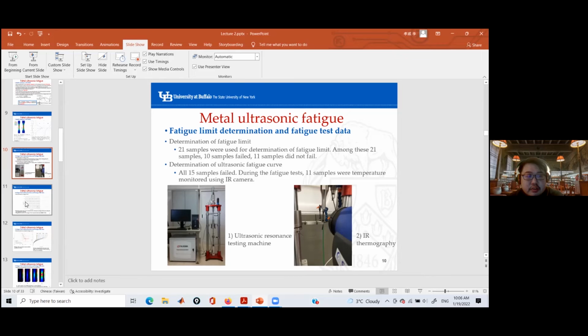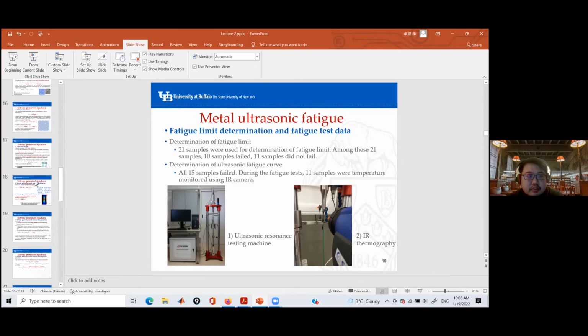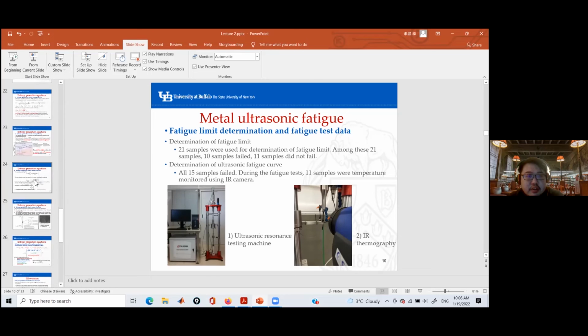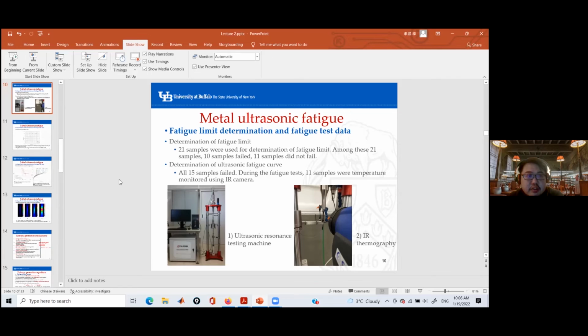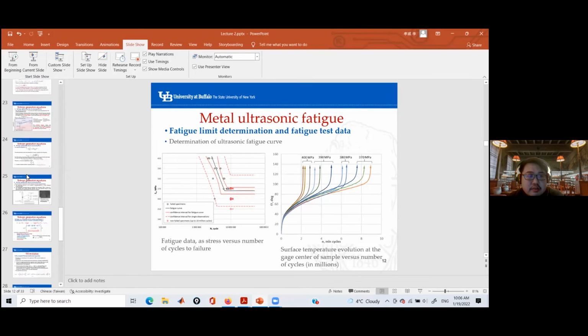So then, do you know the frequency? Say, for example, if you consider two slip planes, each slip plane is having one dislocation, like slip plane 1, and parallel to that another slip plane. So there are two dislocations on the two slip planes. Because of very high frequency, it is possible that they may not see the presence of each other. Like one dislocation is approaching another dislocation, but they don't feel the interactions because the frequency is very high. So they may see only the lattice drag, that is, lattice vibrations will cause the drag for the dislocation movement. So what is the cutoff frequency usually where the dislocation doesn't feel the effect of another dislocation? Did you consider that? Is it because the frequency is very high?